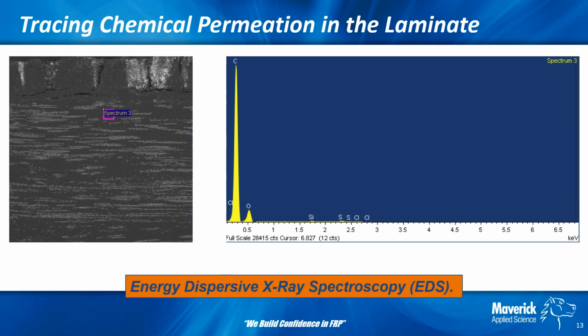So then we actually took 5 locations and samplings from this laminate. We're going to look a little bit further down, just so you see spectrum 3. And so again, you're seeing more carbon, oxygen, chlorine, silica, and then you see the sulfur over here, and it's greatly diminished. It's basically trace elements at this point. And this is really about the permeation into the laminate.